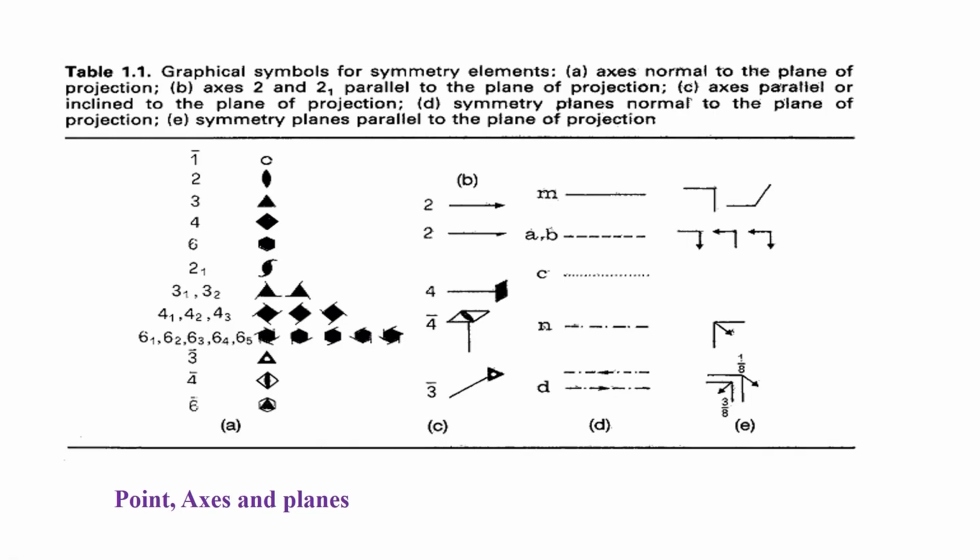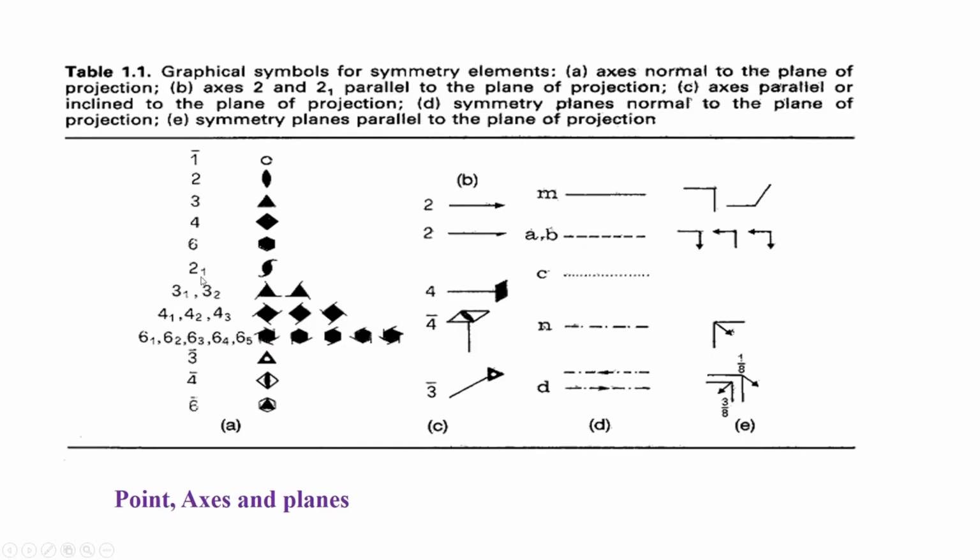half a unit. This translation of half the unit in fact is very important, because what it does now is to take that position which is now at half distance away from the plane of this board, of the illustrated board. It is half the distance away in terms of the unit cell dimension. So, suppose the unit cell dimension in that direction is some c, then it is half that of c. That means the translation component associated with this screw axis is 1/2, 1 divided by 2,